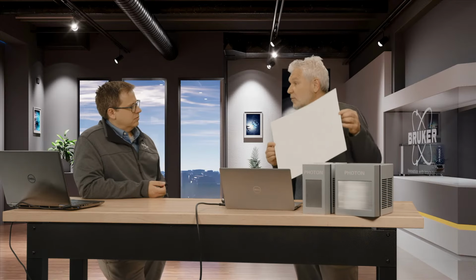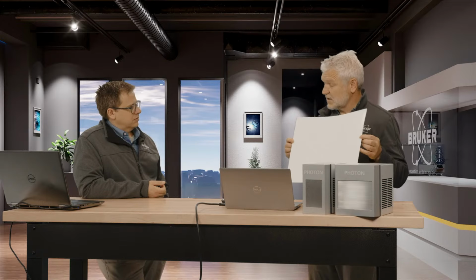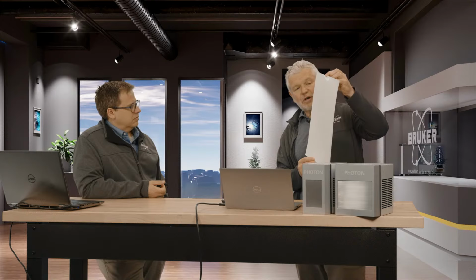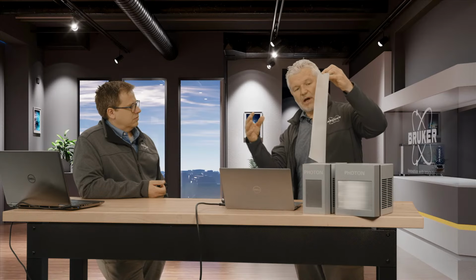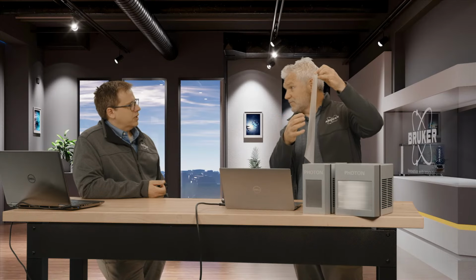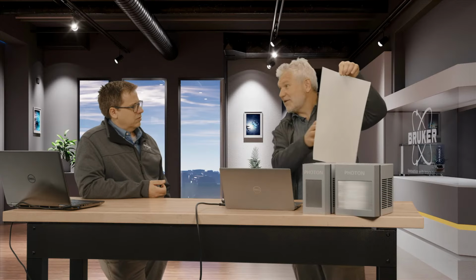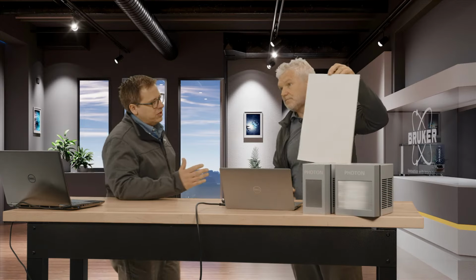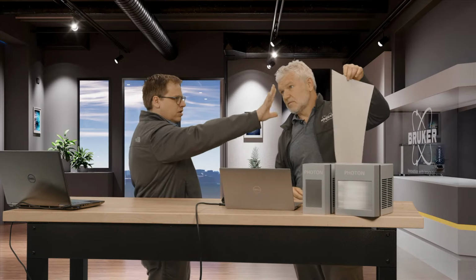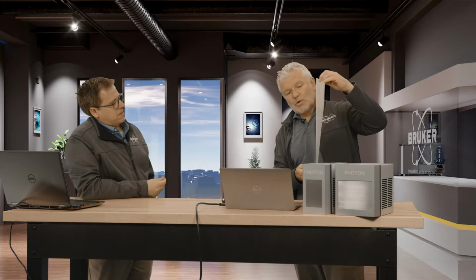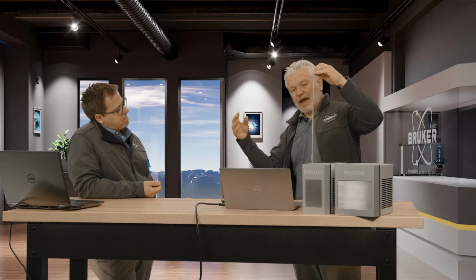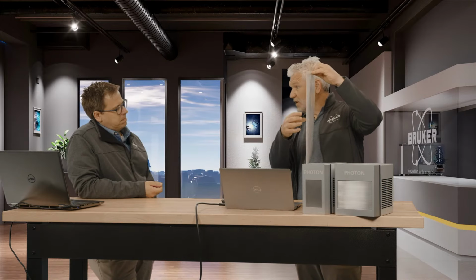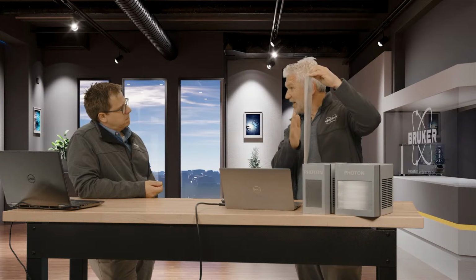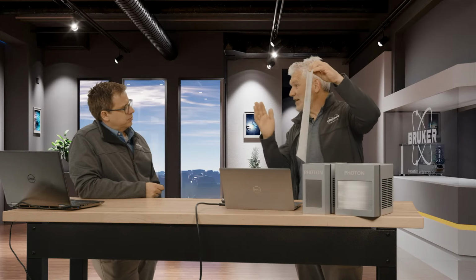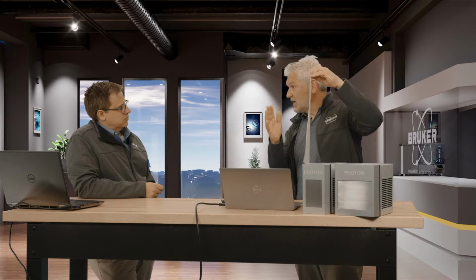We control the formulation, we control the thickness, we control the backing. So how they actually work is you have a reflective area and an active area. I don't know if that comes through on the camera, but definitely this side is glossy, and this side is more matte. So the X-rays hit the phosphor on the non-active side, because the active side is faced towards the sensor.